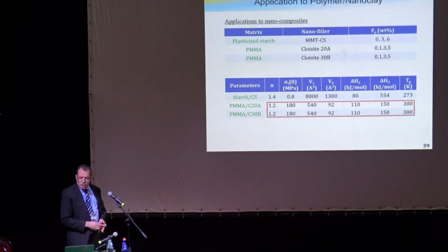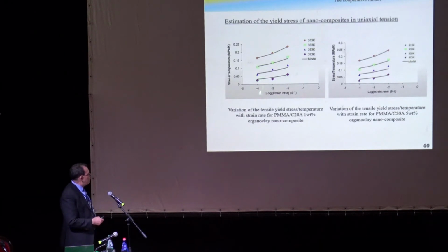And we also applied it to polymer nanoclay. Well, the nanoclay, we have two different nanoclays, Cloisite 20A and Cloisite 30B. These are two different types of nanoclay, and we were able to predict the yield as a function of strain rate. Of course, here we didn't have dynamic loading. We compared to quasi-static loading, and these are experiments. As you can see, the fit is very nice.